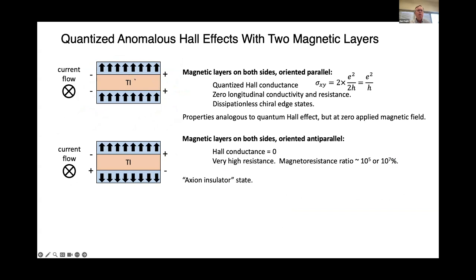But with magnets on both top and bottom and with parallel magnetizations, the Hall conductivities on the 2 surfaces add to give you an integer quantum Hall effect. And you do get 0 longitudinal resistance in this case, and nice dissipationless chiral edge states along the edges. So all the properties you would expect from a quantum Hall effect, but at 0 applied magnetic field if the magnet has a good coercive field.